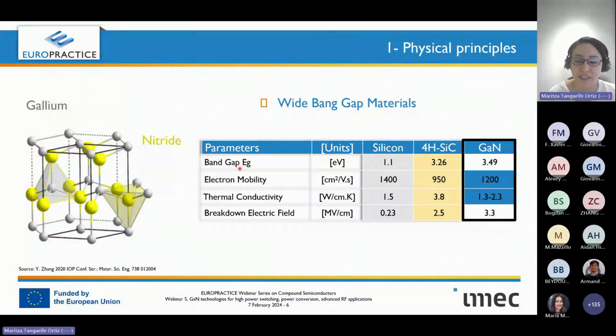So GaN has a bandgap 3 times wider than silicon, so it can operate at higher voltages and frequencies than silicon. If we look at the electron mobility, this is slightly lower than silicon, but still higher than silicon carbide. So electrons in GaN can still travel at a comparable speed with minimal losses. If we look at the thermal conductivity, it is quite evident that silicon carbide outperforms GaN and silicon. So silicon carbide is more effective at transporting heat and has a higher tolerance to temperature and harsh environments.